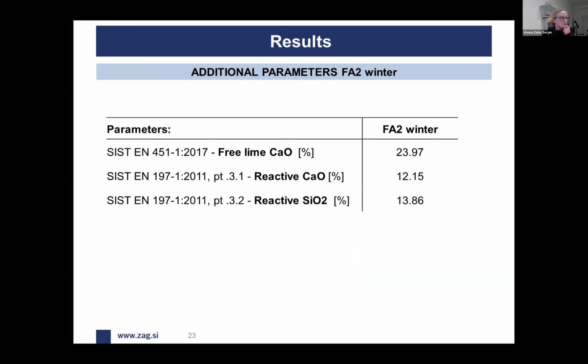But we decided to go further with the FA2 winter ash. Why so? I already highlighted that it didn't show really good potential in the cementitious systems, but it showed very promising features when it's used in combination with water. Combination with water is usually used in geotechnical applications, of course, if there is no need for further stabilization or increasing the strength. So that's why we moved on with further defining the characteristics of this ash.